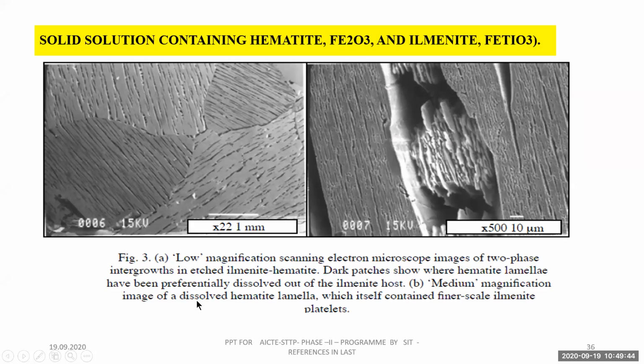For example, see, a two-phase intergrowth of etched ilmenite and hematite. This first image shows dark patches where hematite lamellae have been preferentially dissolved out of the ilmenite host. That is, the major phase is ilmenite, over which hematite is dissolved, and the black lines are showing the dissolved hematite over the ilmenite. And the second image is medium magnification. So this is low magnification.